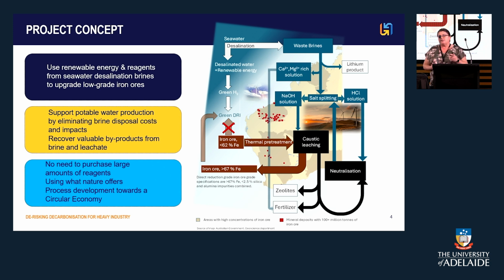On the way, we can also target several byproducts. At the moment, we've already demonstrated that we can make zeolites that meet commercial specifications for use in water treatment and probably as catalyst. We're further investigating geopolymers, which are calcium alumina silicates from the dissolved silicon and alumina, which might be a supplementary cementitious material for the cement industry. And then we're also going to investigate if we can recover that phosphorus that we dissolve as a product.